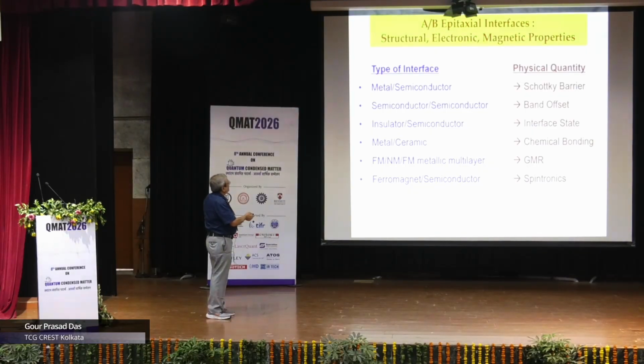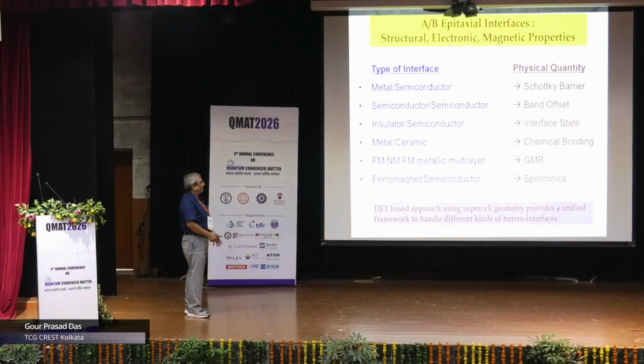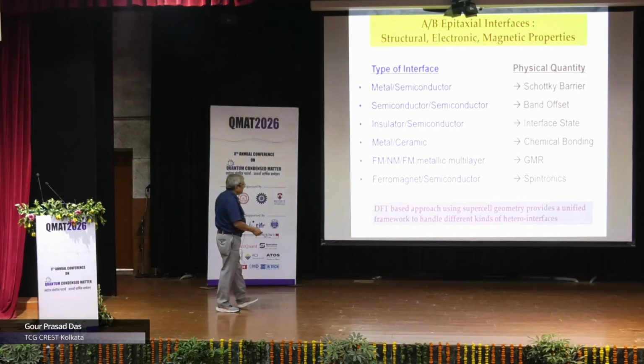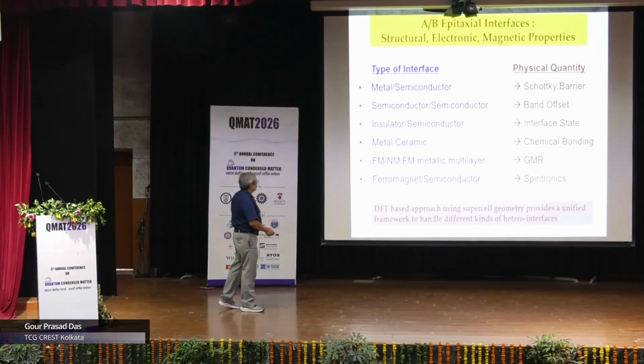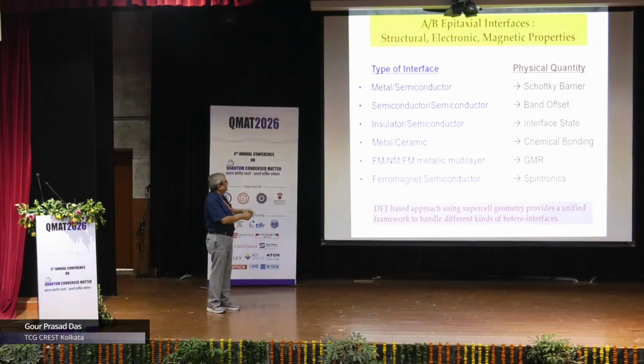So the physical quantity that is extracted depends on the type of interface. For example, if it is a metal-semiconductor interface, the Schottky barrier. Semiconductor heterojunctions, band offset. Insulator-semiconductor, the interface states. Metal-ceramic joints, chemical bonding. Ferromagnet, non-magnet, ferromagnet metallic multilayer, GMR. Ferromagnet-semiconductor, spintronics. So you see, it depends on the type of interface what physical quantity is of relevance. And interestingly, a density functional theory based approach using supercell geometry provides a unified framework to handle all these different kinds of interfaces using one general tool, which is DFT.